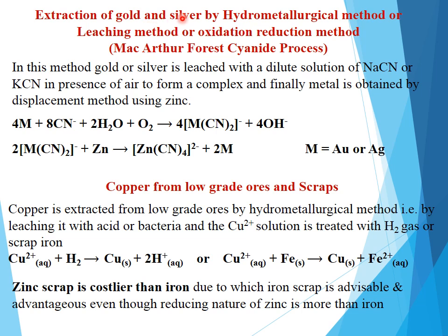Next is extraction of gold and silver by the hydrometallurgical method, which is also called the leaching method or oxidation reduction method, and it is named after scientists, the MacArthur Forrest cyanide process. Gold and silver are already available in native form, but they contain some gangue particles which are removed by this leaching method. In this method, first gold is oxidized and forms a soluble complex, and later in the second step, the complex is treated with powdered zinc, where zinc displaces the gold or silver from the complex, and you get gold or silver in the form of a precipitate.